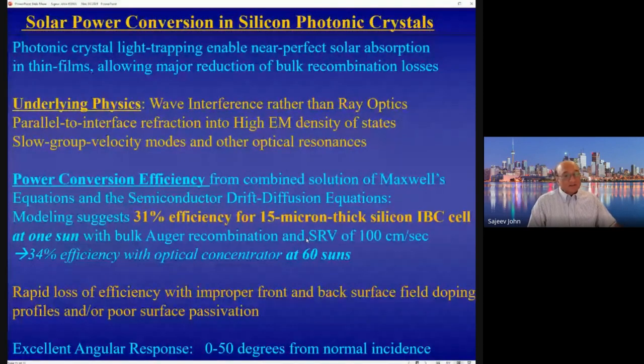I hope what I've convinced you is that photonic crystal light trapping can enable near perfect solar absorption in thin films, even though we're dealing with an indirect bandgap semiconductor such as silicon, which would in turn allow a major reduction in bulk recombination losses. Some of the underlying physics is the wave interference, which leads to parallel to interface refraction effects, high electromagnetic densities of states, slow group velocity modes, and other optical resonances.